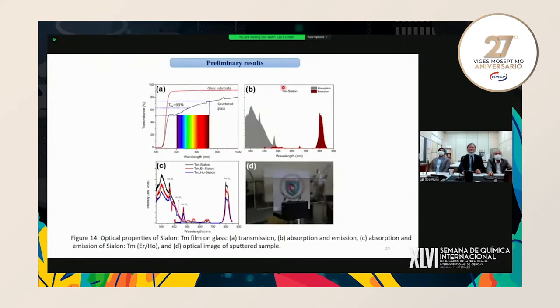So this is data. We look at the glass substrate. Also, we look at the sputtered glass. So we have a good transmittance of the sputtering. When you look at the absorption spectra and emission spectra, not much overlap. This is very important for LSC.